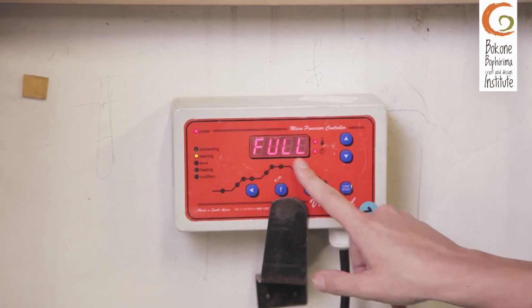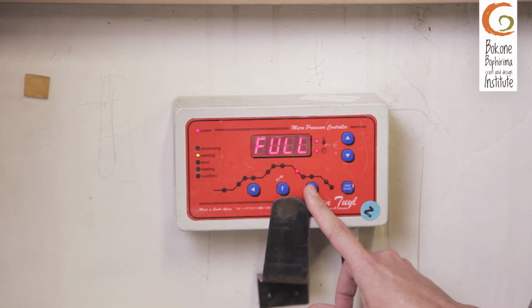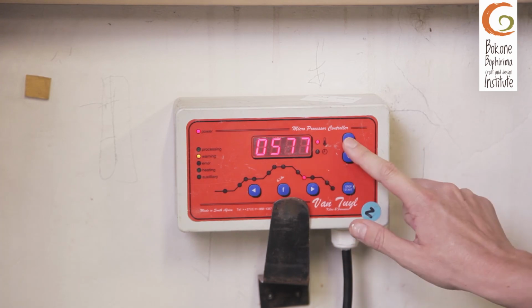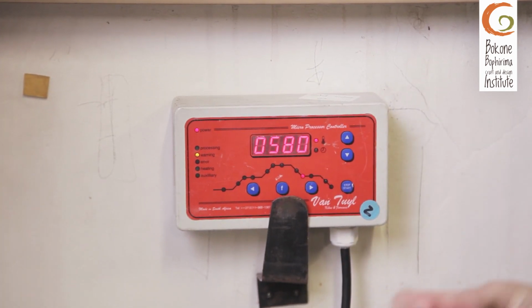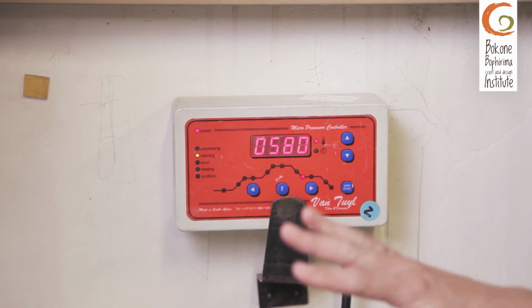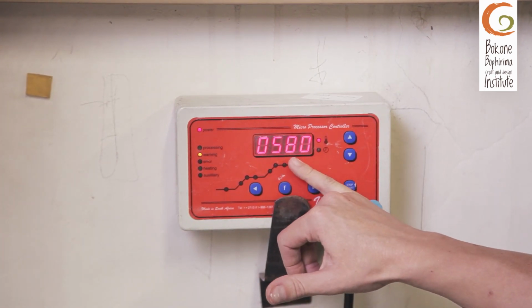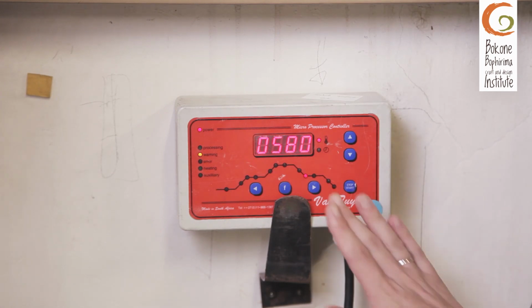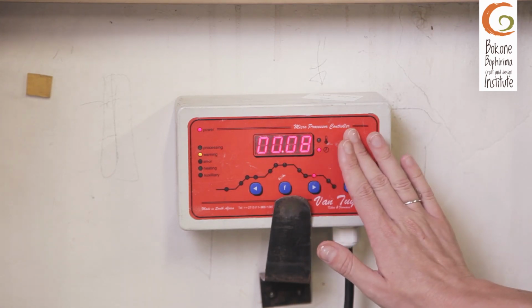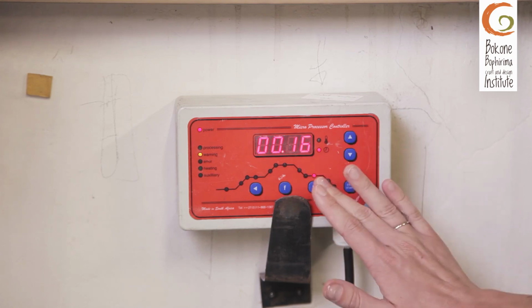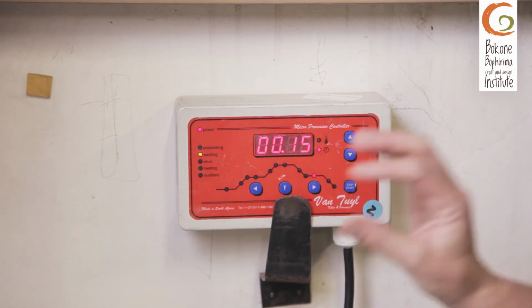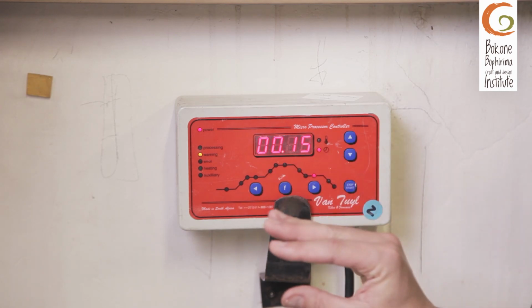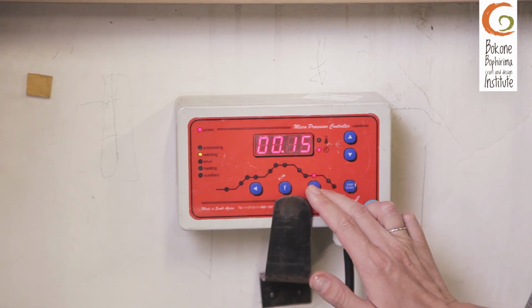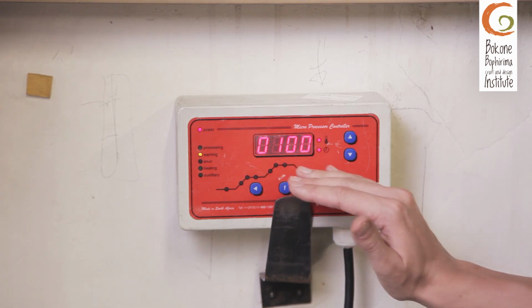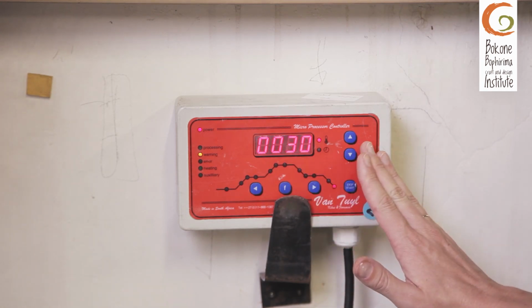I'm then going to bring it down as fast as possible because I'm doing this via the kiln crash cooling, and I'm going to take it down to 580, and this is again where our glass becomes fragile. So we need to make sure from this temperature, from 580, we are bringing the glass down slowly again. Well, first I'm going to hold it for 15 minutes to ensure that the entire piece of glass that we fused is all 580. And then from that, I am going to bring it down 100 degrees an hour, and this process is called annealing, until 30 degrees or room temperature where we can open the kiln.